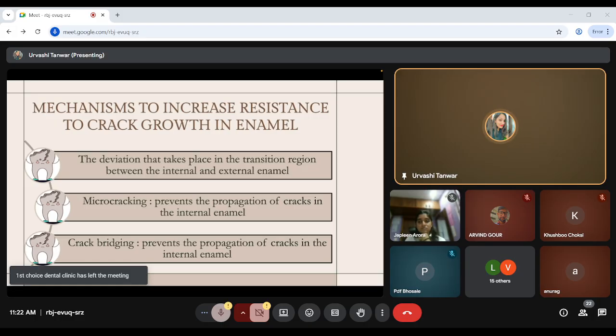And the last one is crack bridging. This prevents the propagation of cracks in the internal enamel. How? These bridges, basically induced by the organic matrix within the internal enamel, promote the closure of cracks thanks to the maintenance of the protein frame, and they stop crack growth. So these mechanisms seem to exist only in the internal enamel, particularly in the zone of decussation, and contribute to making the enamel an extremely tenacious tissue against the propagation of cracks.